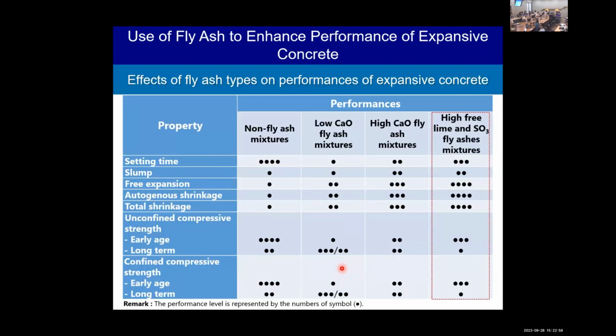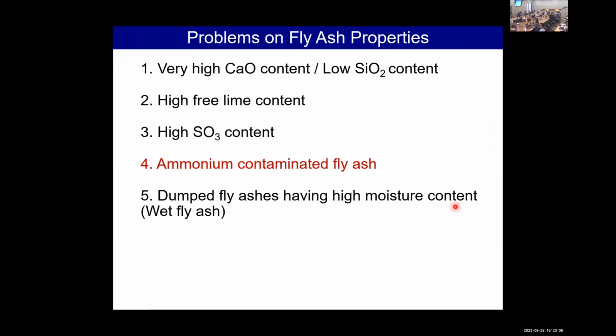And not just the expansion, other properties like the compressive strength can also be improved by using the high free lime and high sulfur trioxide content fly ash in the expansive concrete.